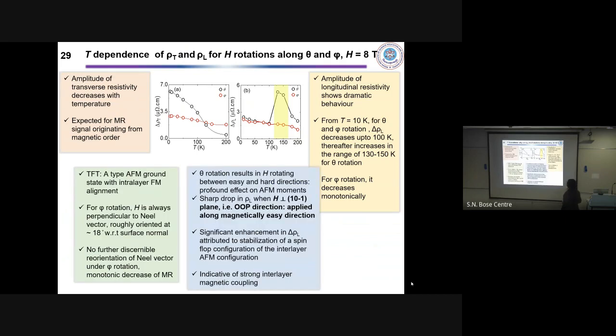So, considering the A-type antiferromagnetic ground state with intra-layer ferromagnetic alignment, for phi rotation the applied magnetic field is perpendicular to the Néel vector, which is roughly oriented at 18° with respect to the surface normal.